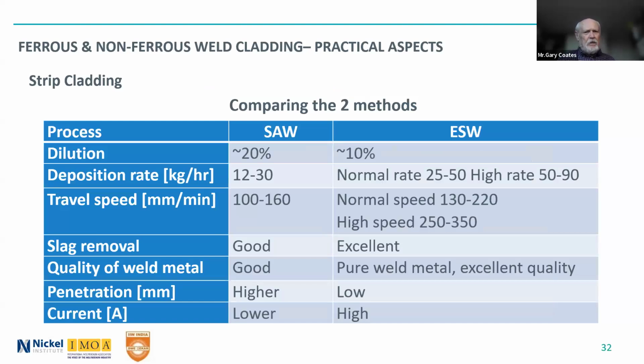The submerged arc one has a higher dilution rate than the electroslag welding. The deposition rate is higher for electroslag welding. Travel speeds are just typical there. You can do some very high speed ones. Slag removal is easier on the electroslag. The quality of weld metal, they're both pretty good. The electroslag is slightly better.